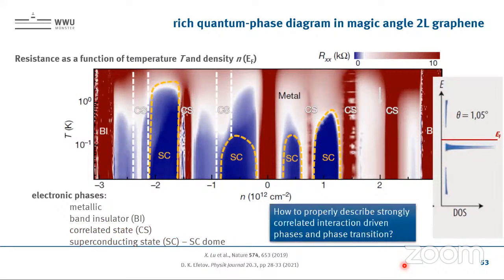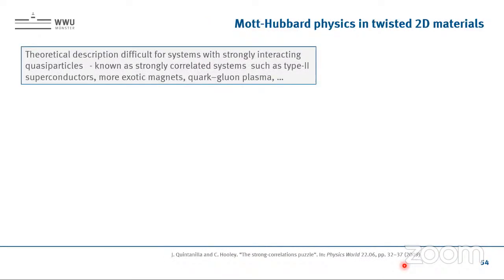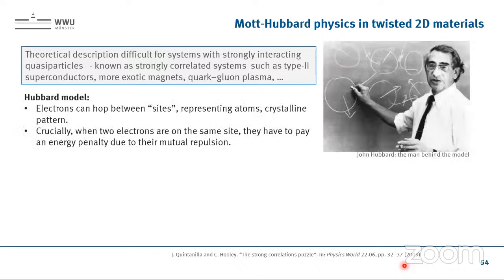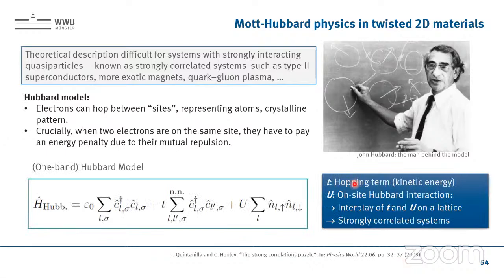So actually, rather briefly, it comes from strong correlations, from an interplay of on-site potential and kinetic energy. It goes back to the so-called Hubbard model. So meaning it's difficult to describe these strongly correlated systems, because we have a lot of large systems with strong correlations, which is really hard to describe theoretically. And here Hubbard defined a model where he said, well, we calculate on a lattice. So we have just two energy scales. We have the hopping term, the kinetic energy, and the on-site potential.